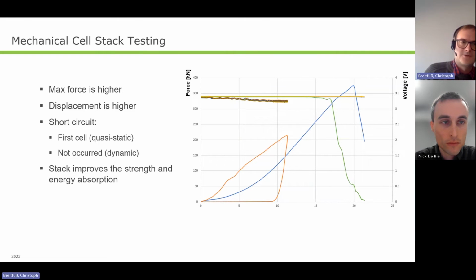And we also tried to reach a short circuit here in the quasi-static test. You can see here we managed, with the maximum force of the test bench, to get a short circuit in the first cell. In the dynamic case, looking at the voltage, we didn't manage to get a short circuit due to the mechanical loading, which is somehow sad for the test result, because it was planned to get a short circuit, but in terms of safety, it's quite a good result.